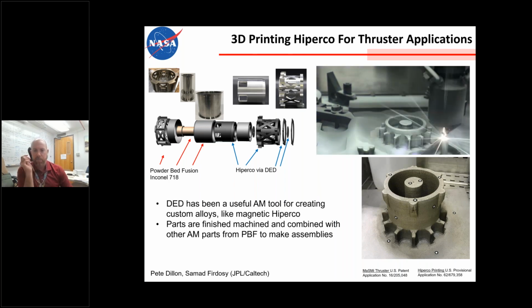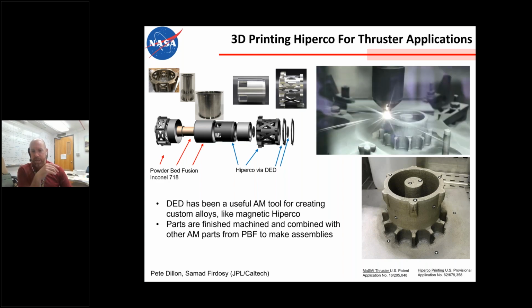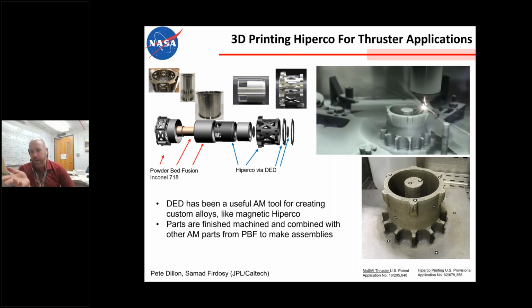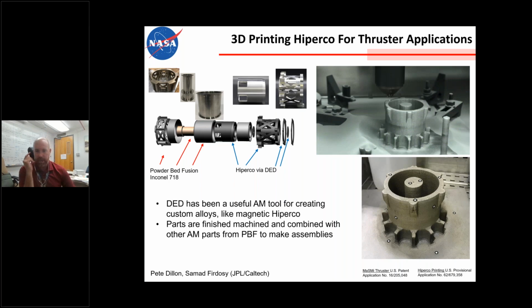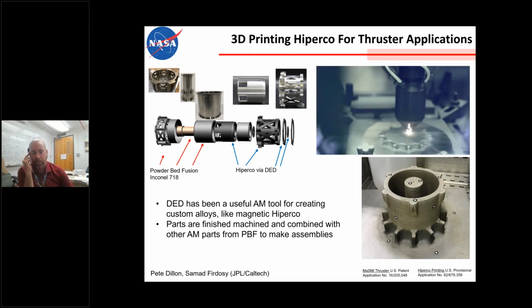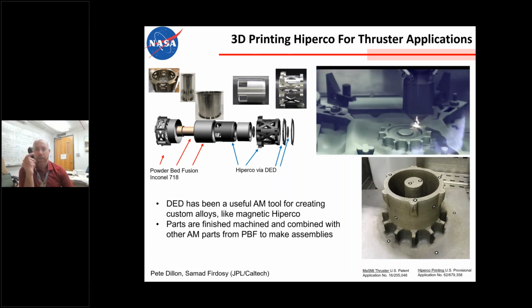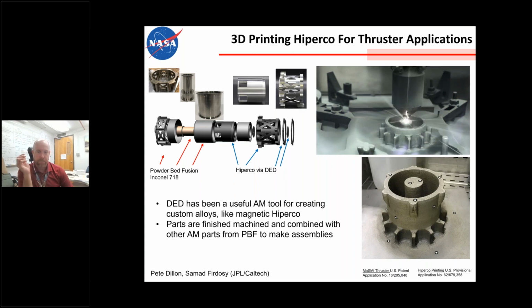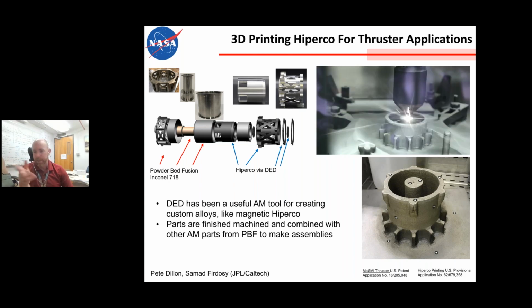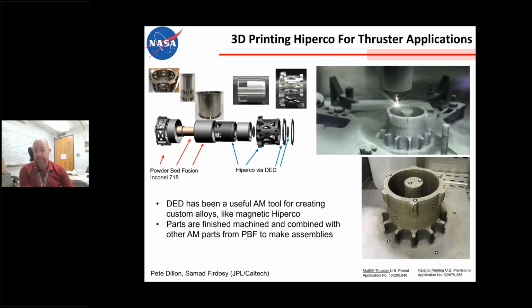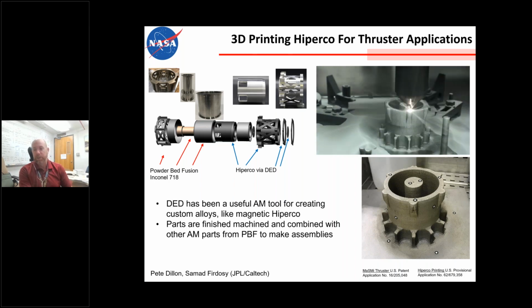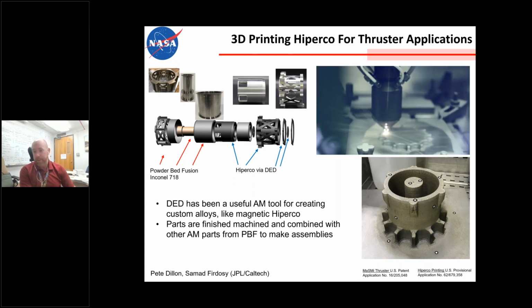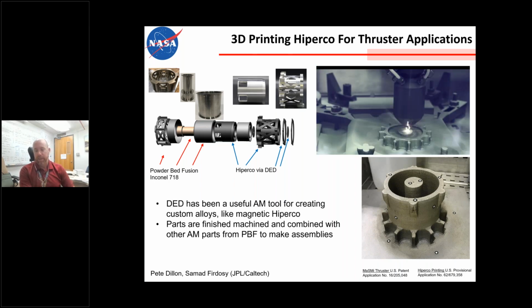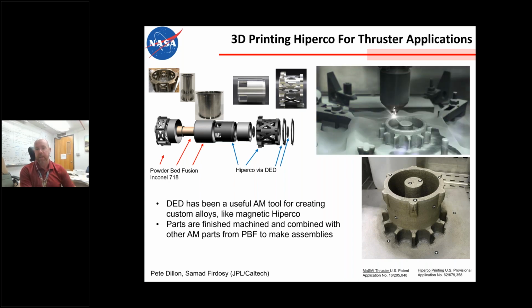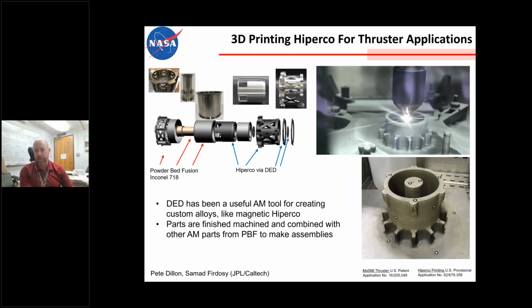So, typically we can 3D print with our DED into near net shapes, and then we do finish machining using our machine shop, which is right outside our additive center. And we can get really unique magnetic properties by controlling grain size in our DED, if not by controlling composition. Just this week, we printed another bimetallic magnetic part that takes this work even further by mixing two materials together.